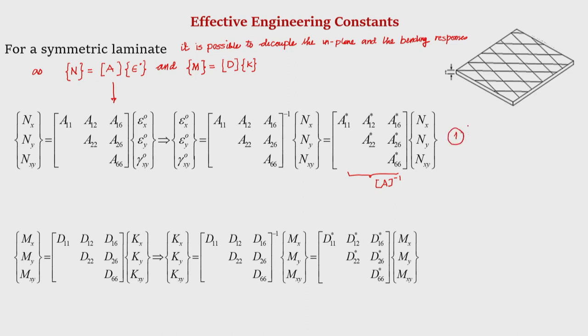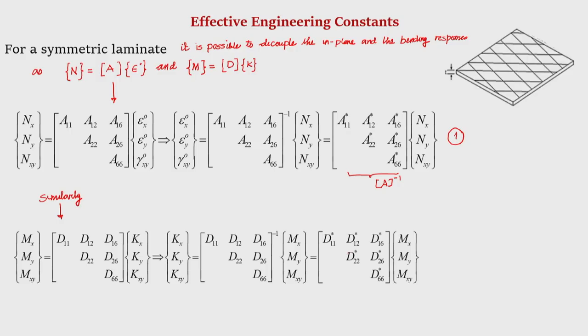Okay. Similarly, we could write the moment curvature relationship, Mx, My, Mxy could be related to kx, ky, kxy by the D matrix. And if we invert this D matrix, we could write the curvatures in terms of the moment resultants. And again, D11 star, D12 star are actually elements of the D inverse matrix. This is nothing but the D inverse matrix.